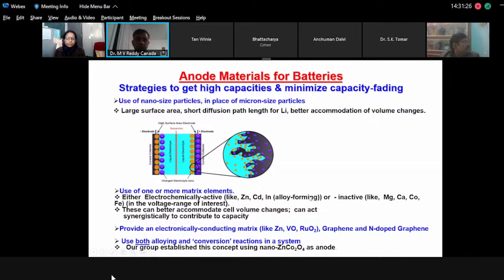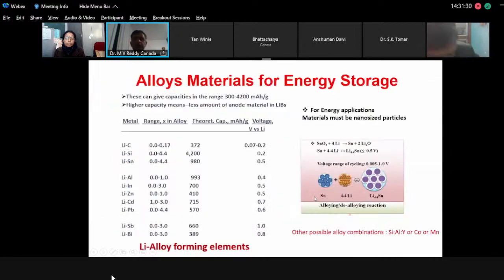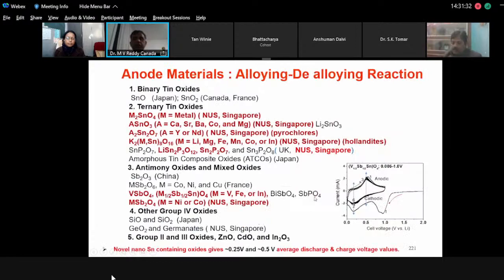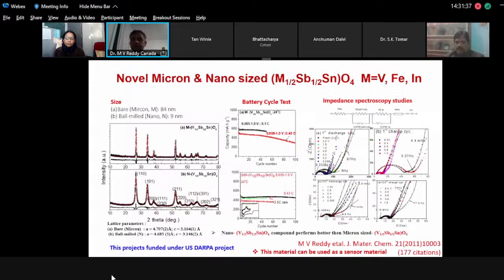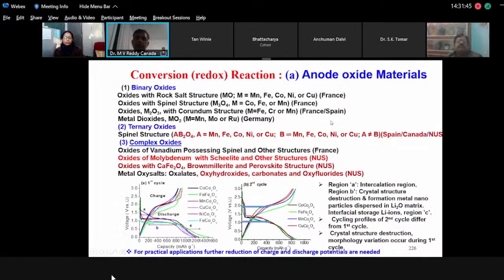So I'm going to, since it's almost 23 minutes, quickly go through. Especially some of the anodes, a lot of tin-based oxides we've also been looking into. Again, a lot of challenges there, although irreversible capacity in the first cycle is a little bit challenging to improve. Here, a lot of oxides people have been looking into.